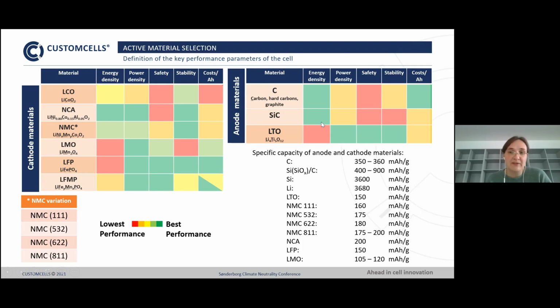New materials with even higher specific capacities, like silicon, are more and more introduced into the lithium-ion battery field. You see that silicon has a theoretical capacity that is 10 times higher than the graphite that is now mainly used. There were some other specific materials like LTO, which is very comparable to these anode materials, has a much lower specific capacity, but it's a very, very stable material where even charged cells can be opened without any problems.